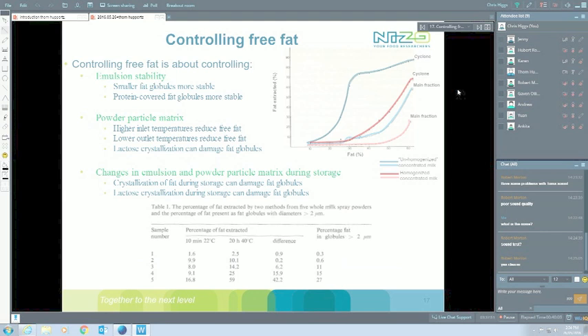One of the things that we typically see there, if we look at controlling free fat, emulsion stability is a very important one. I mean, smaller fat globules are typically a lot more stable, so we need to homogenize properly. The other thing we see is protein-covered fat globules are a lot more stable than normal native milk fat globules. So from that perspective, the homogenization, which actually puts the proteins on the surface rather than the normal milk fat globule membrane that's naturally there, is very efficient. I mean, your inlet and outlet temperatures have a very strong effect on free fat as well because of temperature control, coagulation, damage to it.